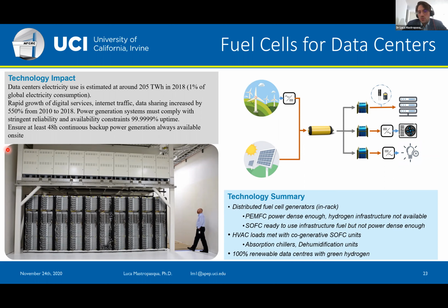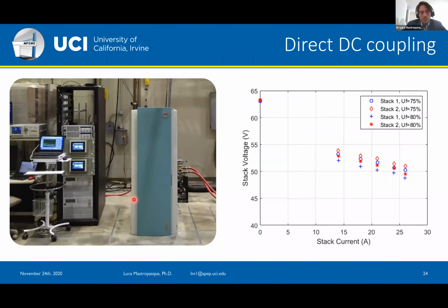So what we first did was to test solid oxide cells coupled with server racks. And this is an example of the test stand that we put together using a 2.5 kilowatt electric commercial solid oxide fuel cell with a direct DC coupling to a server rack. So we removed all the power electronics from the fuel cell, and we directly coupled the output of the two stacks that make up this system to the DC input of the servers.